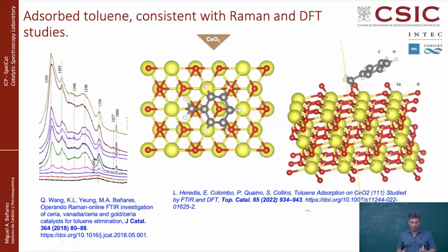How does toluene adsorb at the surface of this material? Computational chemistry is telling you that it will adsorb through this carbon. Okay, fine, we know that. We have observed that the Raman spectra is also telling that. And the infrared is consistent with this.